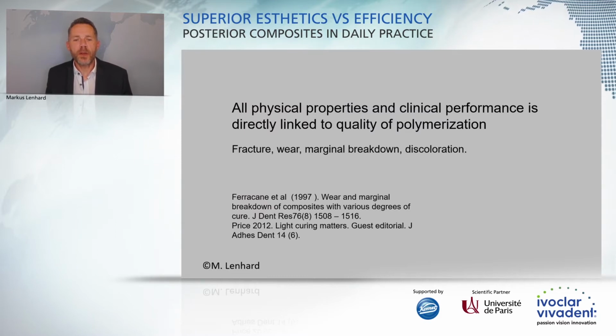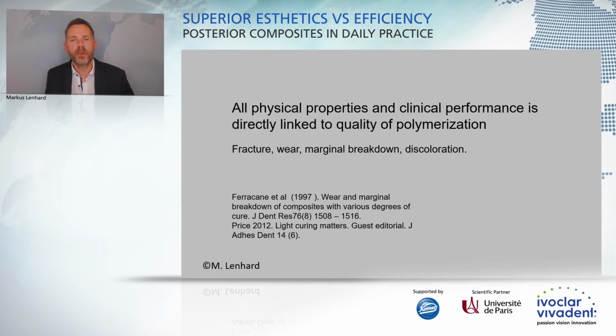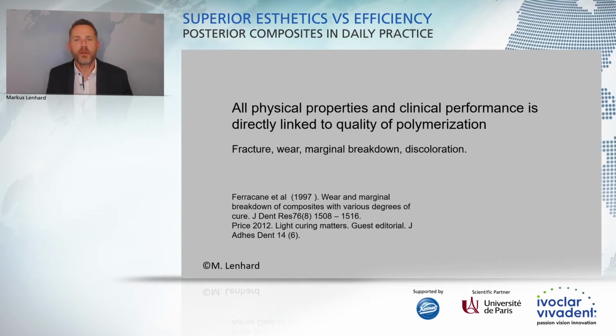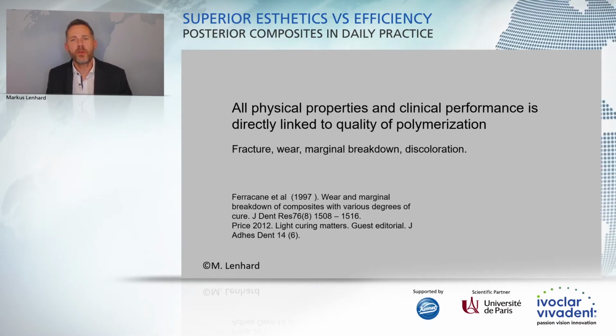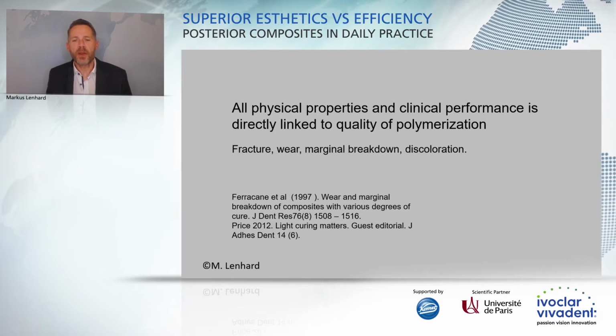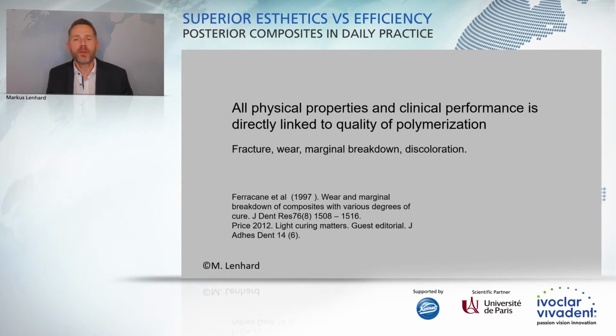Now, when we look at the material parameters, it must be clear that all physical properties and the longevity, the clinical performance of the restoration is directly linked to the quality of polymerization. If you do not polymerize adequately, you get more fracture, more wear, more marginal breakdown, and of course more discoloration. So that must be the major goal, to polymerize correctly.